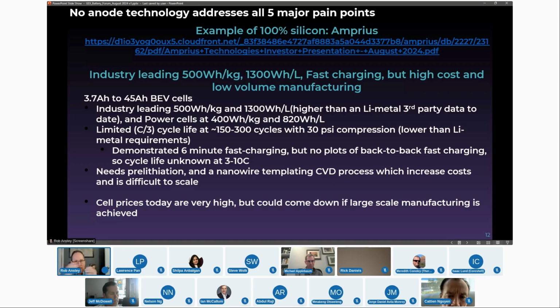But I'd really like them to put out some more plots about repeated back-to-back fast charging. Like, don't just charge fast once or twice, but let's see what happens if you try to charge fast 100 times. They don't need as high compression as lithium metal. They can actually work between 15 and 30 PSI, but I think their best data is at 30 PSI, which is usable in most cases.